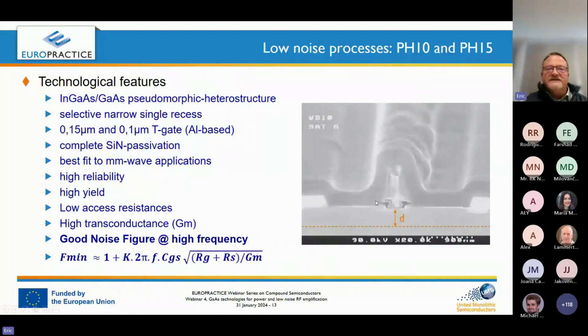Really, this solution is the best fit for millimeter wave applications. It's really high reliability. Why? Because the gate is fully protected, which is really important to keep high reliability. It's also high yield from a process point of view. Why? Because this 2D channel and the doping is controlled by the epi and the distance is controlled by the recess. And because this is a narrow recess, meaning the recess steps are very close to the gate foot, we can keep a very low access resistance in the source and in the drain area. So we keep a very high cutoff frequency. And finally, for the application, a very good noise figure.